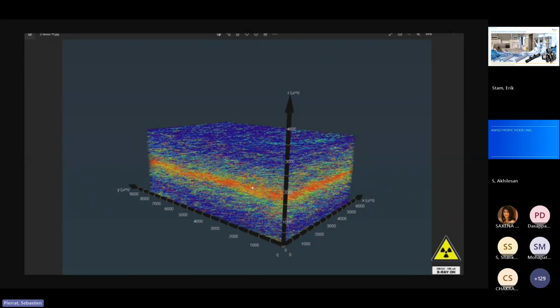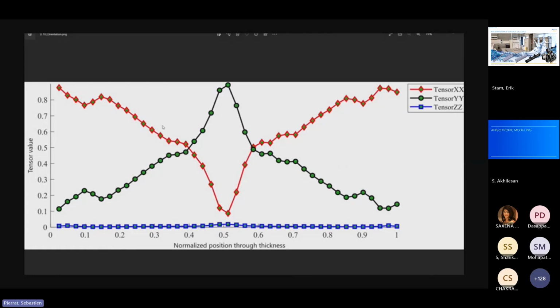The local orientation of each individual fiber is not extremely useful as an input for the predictive engineering. In order to provide some representative data, I average the local orientation of each fiber on different slices and provide the average orientation of the fibers along the thickness of the sample. This is then used for the simulation, and Prasad will walk through the fatigue modeling.